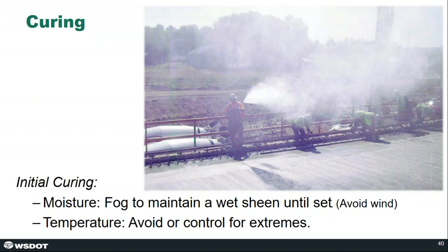We used to use liquid membrane curing compounds, but oftentimes those can't be applied until closer to final set. And so there's oftentimes an hour or more, or possibly several hours of time between finishing and the installation of the first curing system. And curing at the early age is much more important than curing at later times. So this is why we added the requirement to maintain foggers on site.